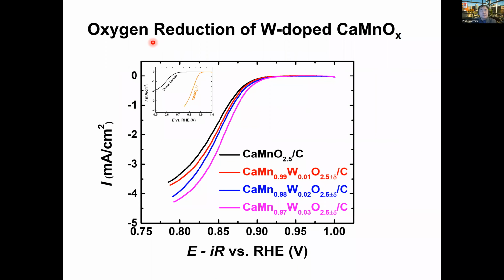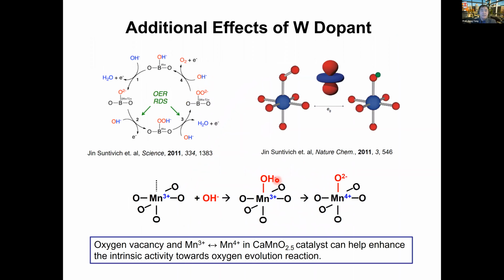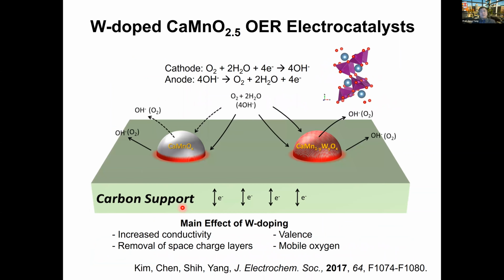It turned out to also happen for the oxygen reduction reaction. This is a polarization curve for this particular system. Of course, the number is relatively low, but that's not the key point. The key point here is that both the oxygen reduction and evolution are helped by the dopant. That suggests to us experimentally that it could be a conductivity improvement on top of the rest of the factors, i.e. the other factor could be, for example, the valence change through the dopant. So that's another additional factor. But the key factor we think in this particular case is the conductivity through the dopant of the metal oxide system. So that says a lot about this particular system.